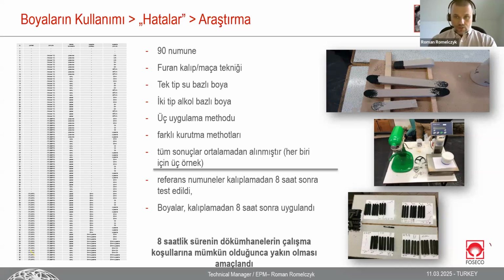After that ZB16 was applied, also a zircon-based coating, the same but water-based. As I said, each of these bars was taken after 8 hours. So after 8 hours, the coating was applied.